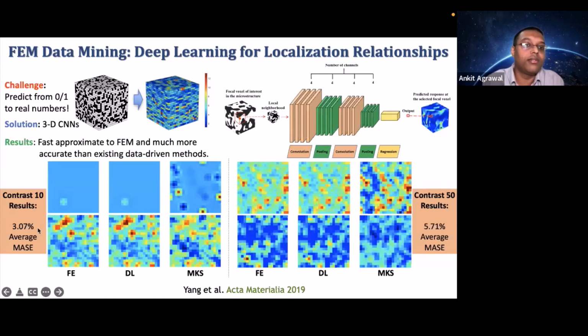So we find here that this is the finite element result, 2 example slices. And this is what we got from deep learning, and this is from their benchmark or baseline model, MKS, and you can see that these hotspots are well predicted using the DL method, but they are missed here. Similarly, for contrast 50, the deep learning result is quite close to the ground truth, whereas this MKS model gives a lot of spurious hotspots. These hotspots are apparently very critical to identify where crack initiation is expected to happen. So it is critical to predict them correctly. Again, more details in this Acta Materialia article.